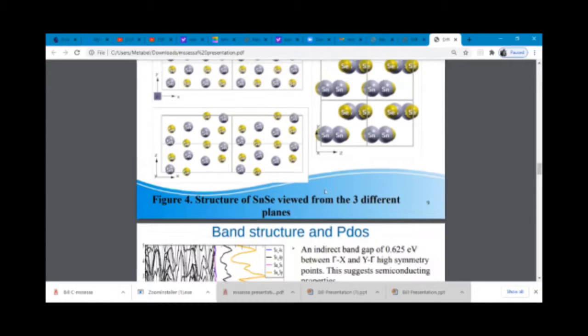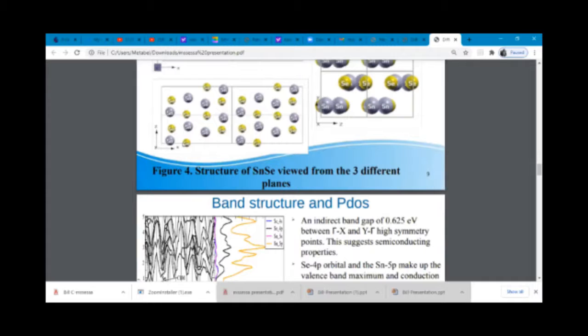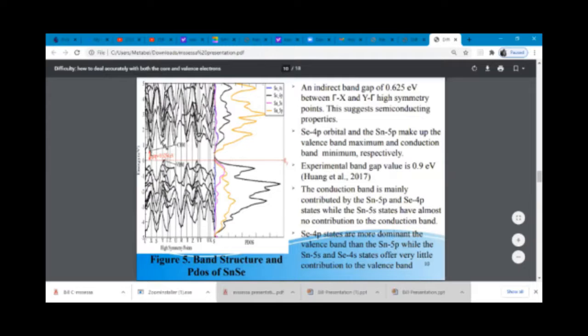So the band structure that was obtained is shown in figure 5. The material was found to have an indirect band gap of 0.625 between the high symmetry points gamma X and gamma Y. It's also shown in the diagram, the conduction band minimum and valence band maximum. From those 2 points, that's where the indirect gap was measured.